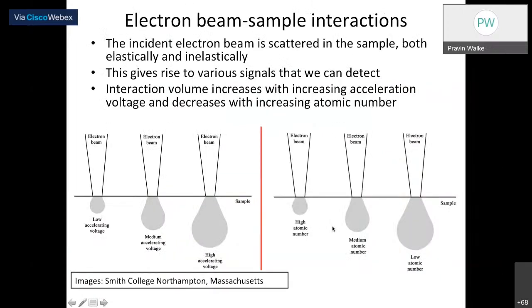Okay, so let's look at what happens when your electron beam and sample interact with each other. Here you have the electron beams. In the left figure you see an electron beam at low accelerating voltage, then at a medium accelerating voltage, and then at a high accelerating voltage. And here you see the sample. The depth of beam interaction at low accelerating voltage is less. If we increase the accelerating voltage, the depth of interaction will increase. That is one thing. The scattering in the sample happens both elastically and inelastically, so elastic and inelastic scatterings occur when the electron beam is incident on the sample. And the accelerating voltage also plays a significant role in the interaction with the specimen, right?